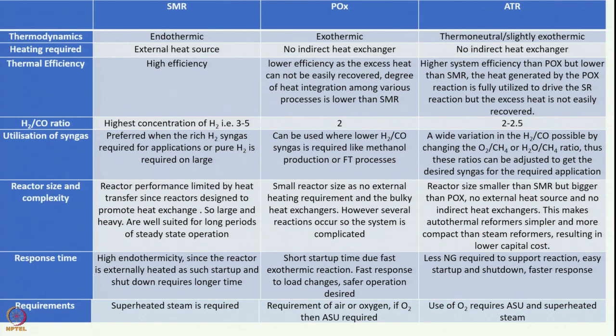Now let us compare all the three processes that we have learned so far: the steam methane reforming process, partial oxidation, and autothermal reforming, based on several parameters. If we consider the thermodynamics of the process, then steam methane reforming was an endothermic process that we have seen, partial oxidation is an exothermic process, and autothermal reforming is either thermoneutral or can be made slightly exothermic so as to encompass the losses that occur in the reactor. In terms of heating requirement, in SMR, the reformer tubes filled with catalyst are externally heated. And in partial oxidation, there is no such indirect heating involved. The heat required for the endothermic reaction is generated within the reactor itself, and the same is true for autothermal reforming.